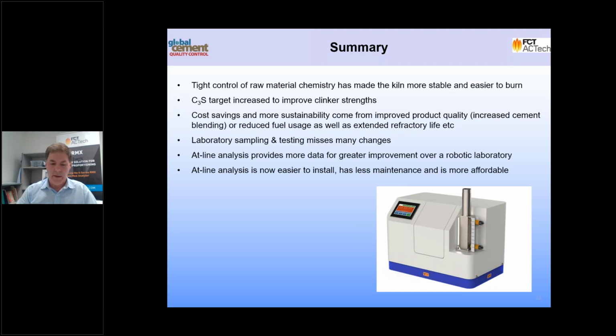So the increased sampling frequency of the raw meal has revealed variations that could not be seen with the laboratory testing. So the addition of at-line data included the kiln dust and the raw mill recycle material, which gave more accurate control of the feeders, further reducing the variation. So the at-line analyzer has shown that it is an essential tool for stable kiln operation, and it has enhanced clinker quality significantly at this plant.